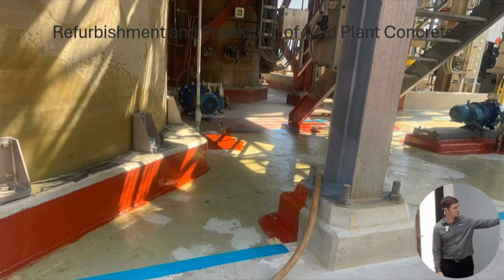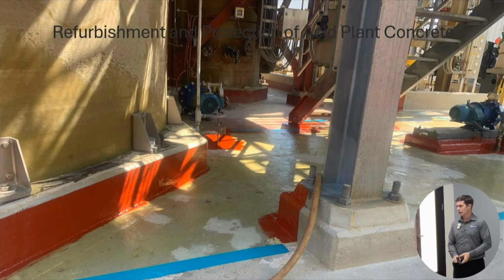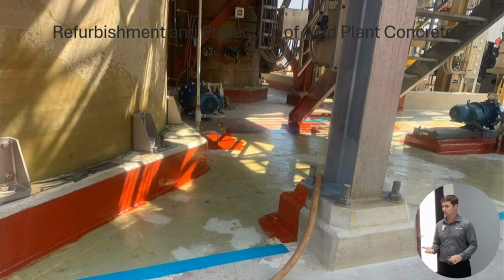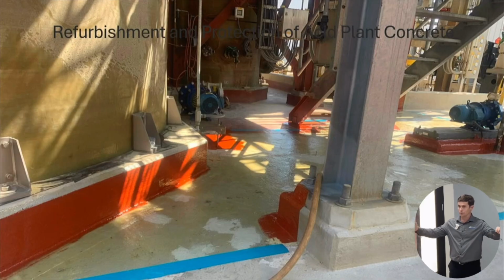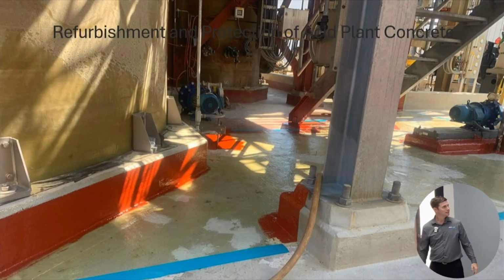More concrete. This utilizes a product called Zippy Screed. Zippy Screed can go down to about 80 mils. So you may use the epoxy polymer concrete to get the really thick stuff, and then you can use the Zippy Screed at the smaller pits, and then also to grade to drain. So you get to that drain in concrete, you definitely want the chemicals to flow into the drain. All too often I've seen inquiries, and the drain is the highest thing in the whole containment. Not ideal.